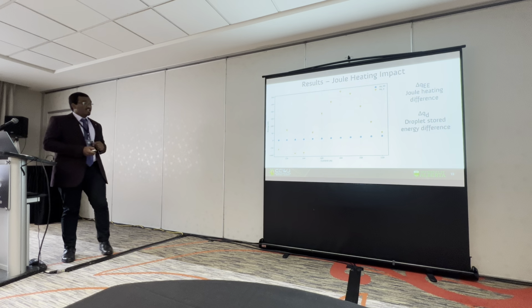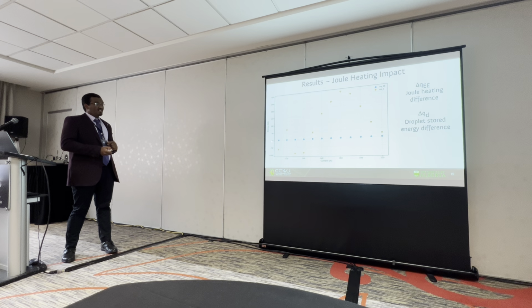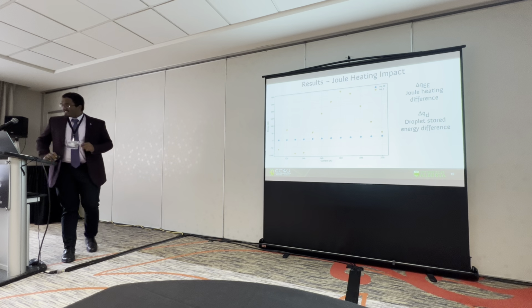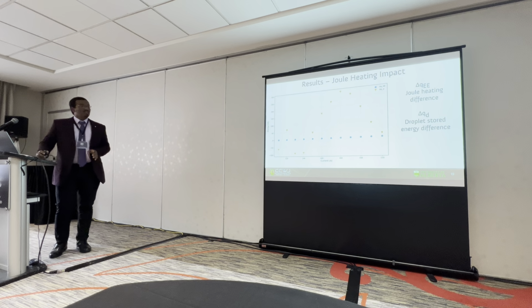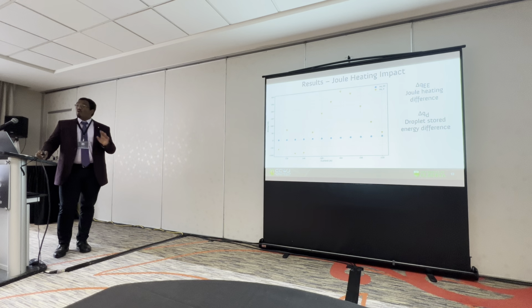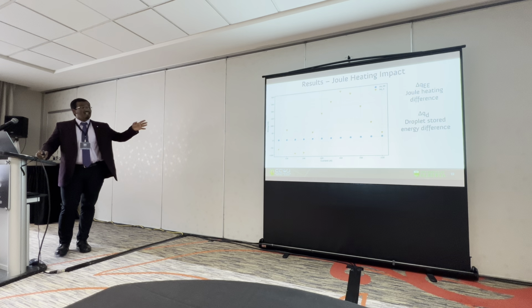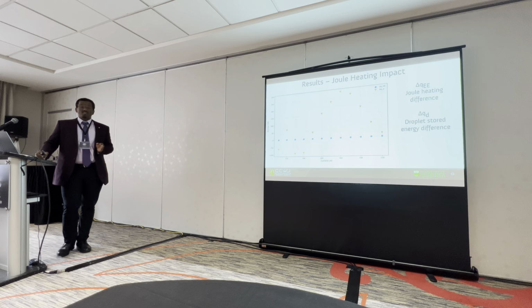Okay, before I get to that, you could see that delta QE is 0. So, frankly, it's not actually 0. It's just that the scale is so much smaller than delta QD, which is in the order of hundreds of watts, that the actual value of delta QE, which is around 0.3 to 1.8 watts, looks very small. That's the reason it's represented close to 0.